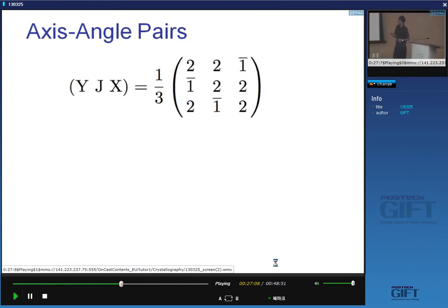Now, here is the relationship between the crystals X and Y that we derived for that duplex stainless steel. And it looks like this. It's a nice, neat matrix, and I can take this fraction out common to turn everything into an integer there. Okay, so can you tell me what the sigma value is between these two crystals, the coincident site lattice? I've taken a fraction out here to convert everything into an integer, and therefore this is a sigma 3 relationship between the two crystals, and when they touch each other, 1 in 3 of all lattice points will be common to both crystals. So this is actually a twin orientation between the two crystals.